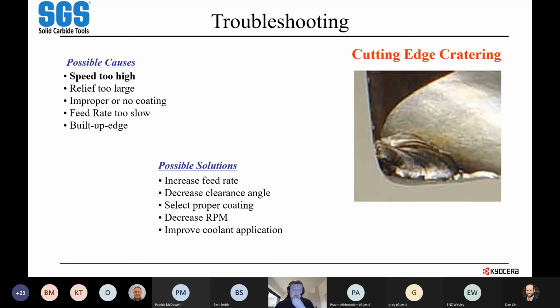It also can be caused from a buildup on the edge. It's going to cause the chip to flow into it abnormally, which will cause irregular wear patterns and whatnot, and again will ultimately lead to cracking. So you can always try to increase your feed rate, get a little bit heavier cut, get the chips moving through a little bit faster, and get the heat pulling out with the chip, as well as playing with your coolant. Ultimately, if it's a heat problem, coolant can play a big factor in trying to fix that.